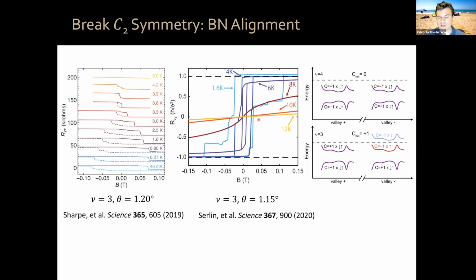And then, the following year, the group of Andrea Young published this very interesting experiment where they actually measured the quantized anomalous Hall effect, okay? So quantum Hall effect at zero magnetic field in, again, magic angle twisted bilayer graphene aligned to the hexagonal boron nitride. And again, you can understand this. This was a filling factor of 3, okay, where we had gone through this cascade of phase transitions, and all there was is one flavor polarized band to be filled, after nu equals +3, okay?